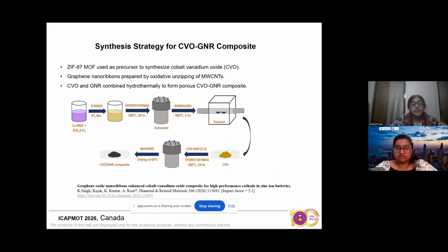For this, we have used ZIF-67, that is the metal organic framework. Metal organic frameworks are always better to use because they are porous structured crystals composed of metal clusters linked with organic ligands. They possess control over pore size, and readily available metal sites make them desirable for various applications. So we have used this ZIF-67 MOF as a precursor to synthesize cobalt vanadium oxide.